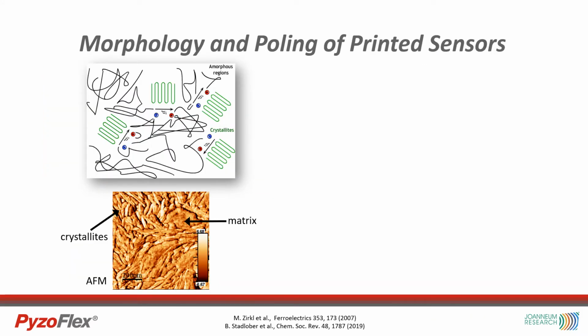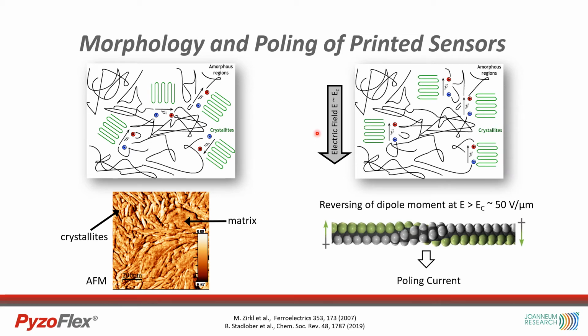As you might know, PVDF-TrFE is a semi-crystalline copolymer where the ferroelectric crystallites are embedded in an amorphous matrix, as shown in this AFM image. They appear as elongated rice grains or spaghettis. After printing, the crystalline dipole moments are randomly oriented. Therefore, an electric poling field has to be applied in order to preferentially align these dipole moments and thus induce a macroscopic non-vanishing polarization across the layer.